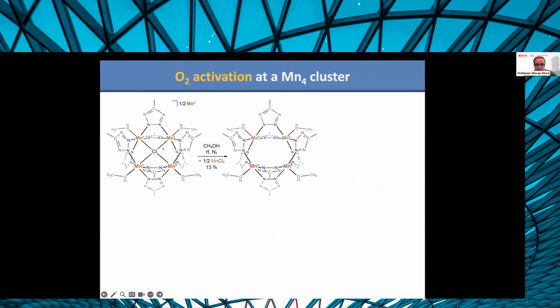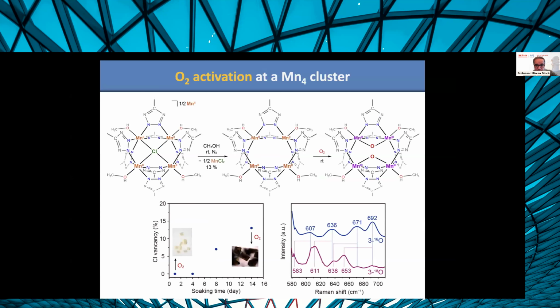But what we found is that as you activate this material, basically trying to remove the solvent, as many of us do when we measure, say, adsorption isotherms, we found that just soaking the material in methanol removes some of the chloride along with charge balancing manganese from this structure, thereby leaving an empty square planar manganese 4 cluster. So we naturally thought that since manganese is so redox active, it might actually react with something like oxygen. And what we found is that indeed from the original material, which is all manganese 2 and therefore colorless, simple exposure to oxygen immediately colored the material into this deep purple.